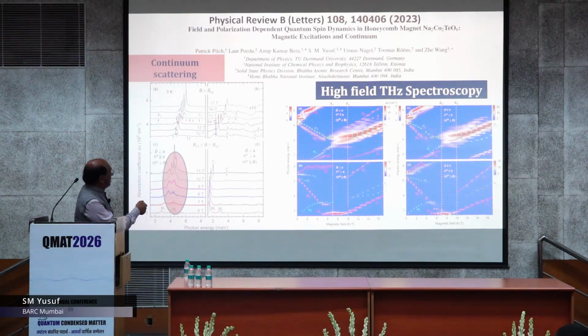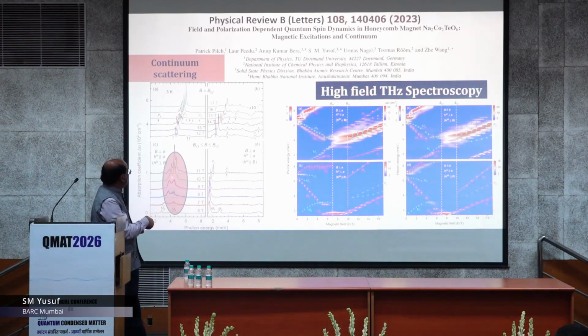And it was extended by doing high field terahertz spectroscopy, where we could see continuum scattering, in collaboration with Professor Wang, and this is a very novel technique, in fact, to look at the quantum correlations.